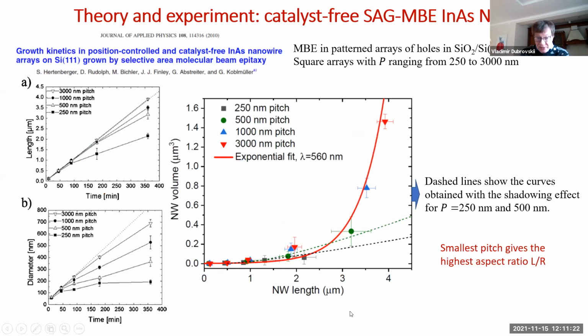So then I compared this prediction to the results published by Hertenberger, basically from Gregor Koblmüller's group, long ago. What they did, they grew by MBE indium arsenide nanowires without any droplets in square arrays of different pitches ranging from 250 to 3000 nanometers. And they measured the mean length and the diameter, which increased sublinearly with the growth time. But if I replot this in terms of nanowire volume versus length, I can see that all the results, imagine the pitches are very different, there is a huge difference between 250 and 3000 nanometers pitch, but all the results within the error bars follow this exponential curve that was predicted.